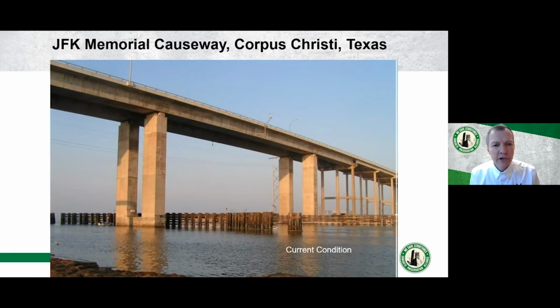I had the privilege of being able to inspect that bridge along with the then chief bridge engineer for Texas DOT, and generally it is in really good condition. It has one issue, a detail that they probably didn't know about at the time when they built the bridge. The end anchorages for the post-tensioning actually come up and end in the deck slab, so the anchorages are somewhat sensitive to getting contaminated with water or having water infiltration because the anchor pockets end in the deck. Other than that one issue, the structure has served very well and has been in good condition.